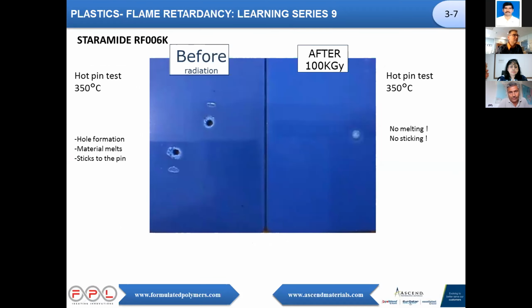What happens? If we see what happens in these pictures, on the left side you have a plate that has been tested, 350 degrees C, 1 kilo, and of course you are more than 90 degrees C above the melting point. So what happens, as you know, in plastics, once the melting point is over, then the material melts down. And you see here the print of the pin. It goes through the part. And if you look at the pin, the material is stuck to the pin. There is a hole formation.